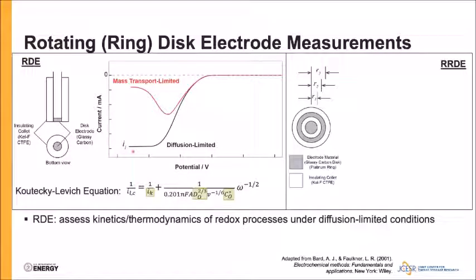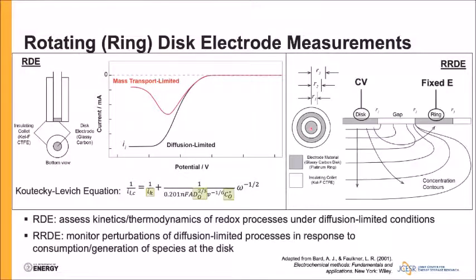Rotating ring disc relies on basically the same setup, but with the addition of a ring electrode to the outside of your working disc electrode. What that allows you to do is generation-collection experiments, where as you generate or consume a species at the disc electrode, you can monitor perturbations to the current on the ring electrode. In this case, we'd be consuming zinc or whatever species for metal deposition, and you would see a decrease in the steady state current at your ring electrode.